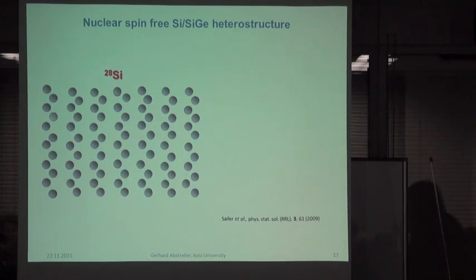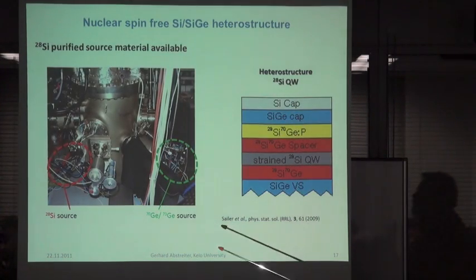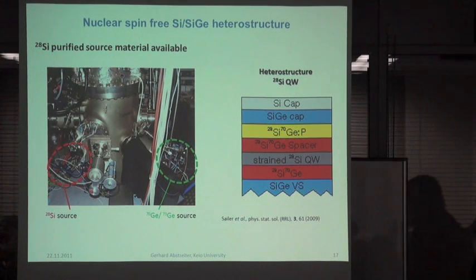So we can just grow the active layer with silicon-28, and then we have negligible nuclear spins, and also the surrounding we can grow with germanium-70 instead of 73, and then we have no nuclear spins in the system, and then we expect even longer, let's say, decoherence times in silicon.